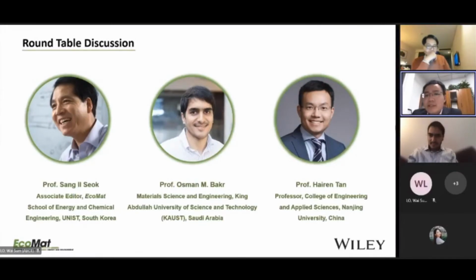Because without this ITO, if we directly spin coat the PEDOT:PSS layer on top of the wide bandgap perovskite, it will dissolve the wide bandgap perovskite because it is a water solution of PEDOT:PSS. So as I mentioned, the critical layer is the atomic layer deposited tin oxide layer. This layer can protect the front wide bandgap perovskite subcell, so that we can easily spin coat the PEDOT:PSS layer on top of that without any damage. I think this is very critical.